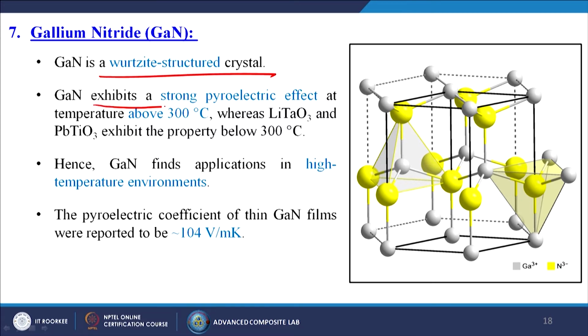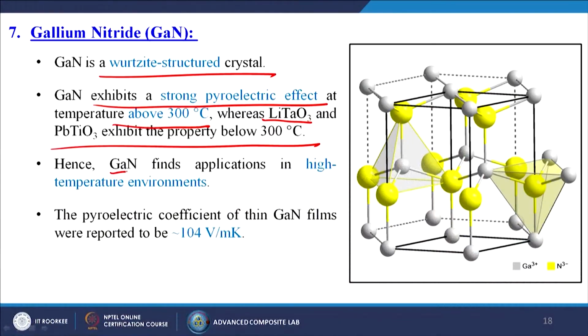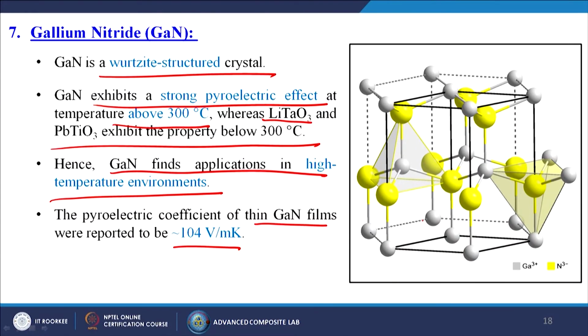Gallium nitride exhibits a strong pyroelectric effect at temperatures above 300 degrees centigrade, whereas LiTaO3 and PbTiO3 exhibit the property below 300 degrees centigrade. So, that means for these particular materials you need the higher temperature. Hence, gallium nitride finds applications in high temperature environments. The pyroelectric coefficient of thin gallium nitride films was reported to be 10^4 volt per meter Kelvin. So, basically this is the standard structure of the gallium nitride which can work at higher temperature.